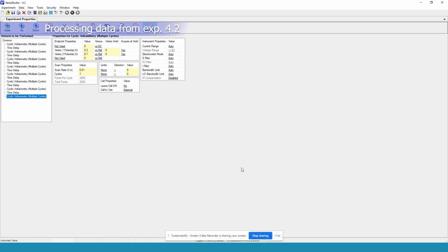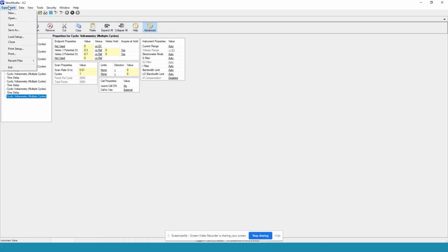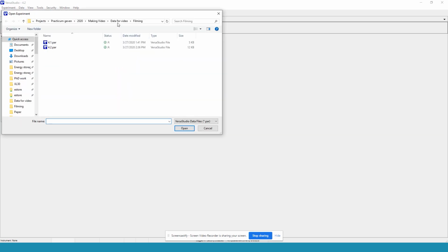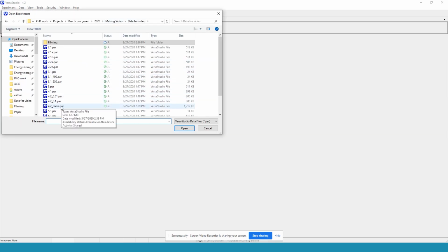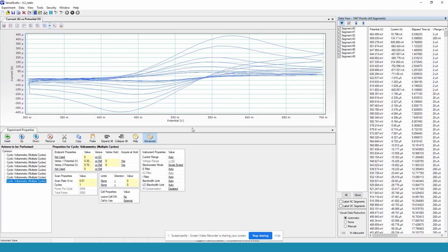So now we can have a look at what the data from this experiment actually looks like. So we can open the data from experiment 4.2, which is this one. And we can instantly already see that the scan rate does indeed have quite a large effect on the behavior of the experiment. We can see that the peaks of the experiment, which were done in otherwise identical conditions, change quite drastically with the change in scan rate.